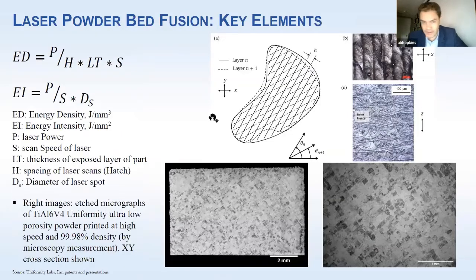All right, so a couple of equations that maybe make this a little more manageable. ED, energy density: power, that's the laser power, divided by the hatch spacing. That's if you're doing scan tracks; look at this figure in the middle top. You space them a certain number of micrometers apart, say between 100 and 300, usually around 150 or 200, depending on the material, in actual operating regimes.